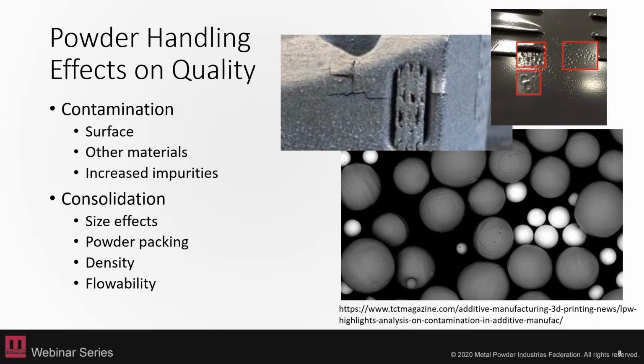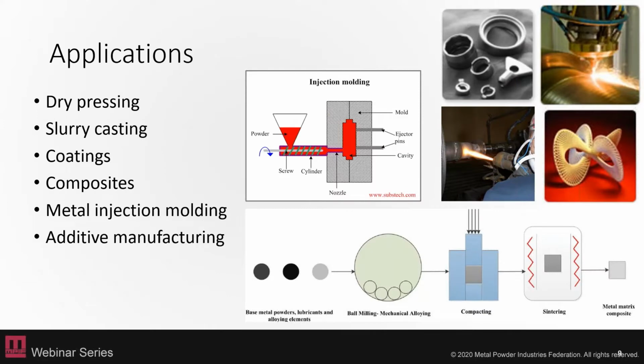And then again, your powder handling is going to have an effect on your consolidation, whether that's during shipping, where jostling of your container caused size segregation to occur in the container, and then you're using the finer powder pulled out on the top from the beginning, and then you're getting a different powder flowability or different density in your part or different packing from your different size distribution. That could have a lot of issues downstream. So those are things that you need to be aware of.